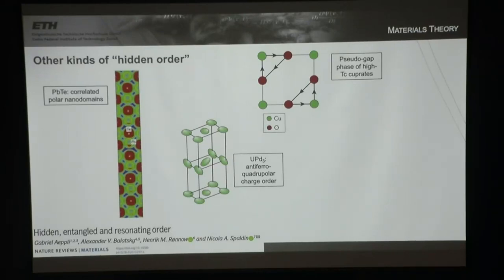And then this is one of my personal favorites, lead telluride. It's a very good thermoelectric, so it will conduct charge, but it scatters a lot the phonons, the lattice vibrations. And this was not understood until it was identified that there are polar nanodomains. If you look at the lead atom here, you see that the electrons in red are separated from the lead ion, so there are these little dipoles in the crystal structure. These are correlated, but they don't completely lower the symmetry to a new phase. But this kind of hidden correlated order is believed to be responsible for the good thermoelectric behavior of lead telluride.